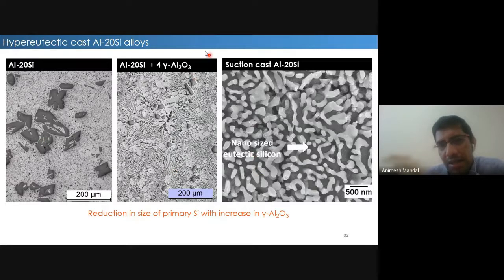Similarly, for the same alloy, we tried to cast it using a technique called suction casting, which is a very high cooling rate process. So it's also possible to generate, I will say, a nano-sized eutectic silicon. Of course, not the entire volume fraction, but there are points, and you can see from this particular microstructure.